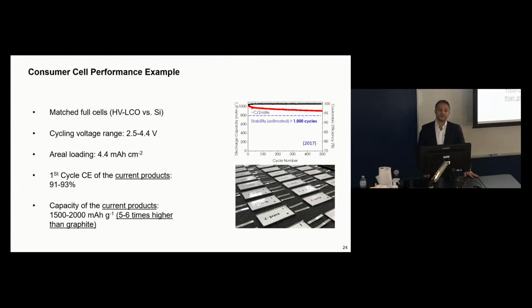And so with significant resources, and again, it took us much longer than we expected, but the company did develop high-performance anodes, drop-in replacement anode materials that would offer very good performance at high area loading. Area loading is how thick your electrode is. It is important to produce the loading that will be compatible with industry standards. The higher the better, because you will use less inactive material in the cells. And so high performance characteristics: high loading, low first cycle losses, and high capacity.